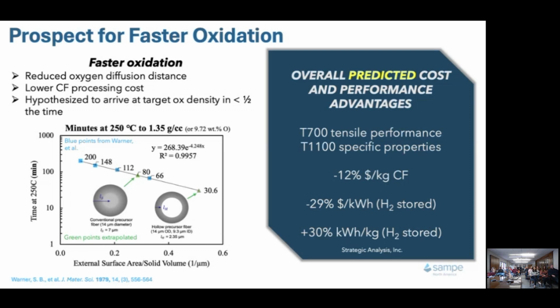And we follow that with the density of the filaments, which we measure by a density gradient column. 1.35 grams per cc is an ideal oxidized density. The starting pan fiber is around 1.18 grams per cc. When you take a really large diameter fiber, the number of minutes at 250 degrees C to arrive at a density of 1.35 is high. So that's the point up here. As we make smaller and smaller filaments, the number of minutes at 250 to arrive at the density marches downward. In this case, the diameters associated with the production of current pan-based carbon fibers point to something on the order of 66 minutes at 250 C to arrive at that density.